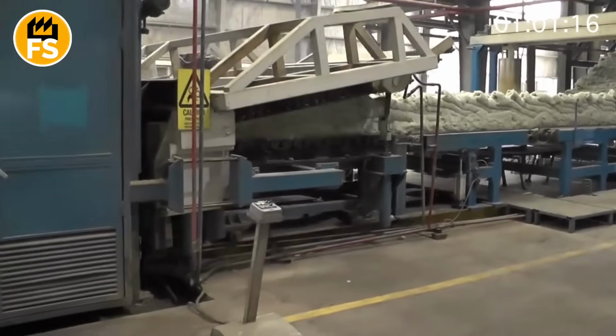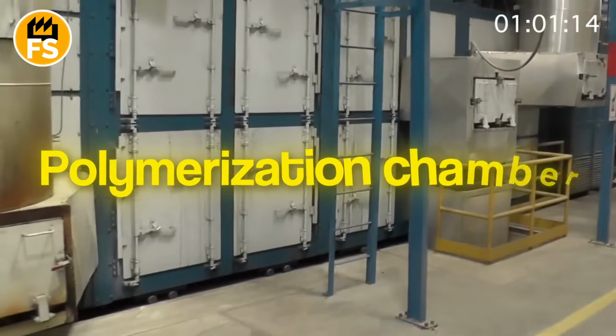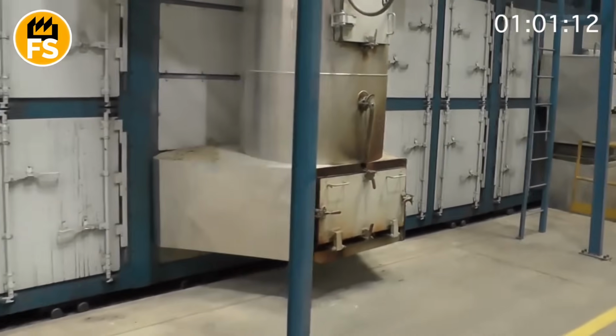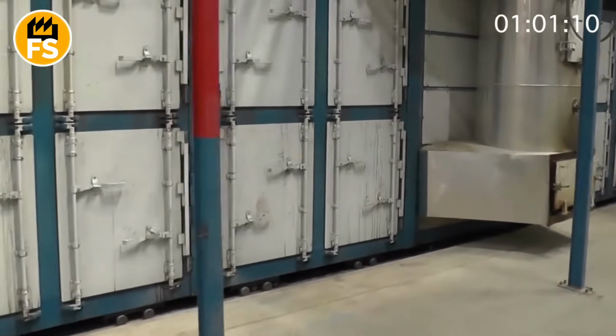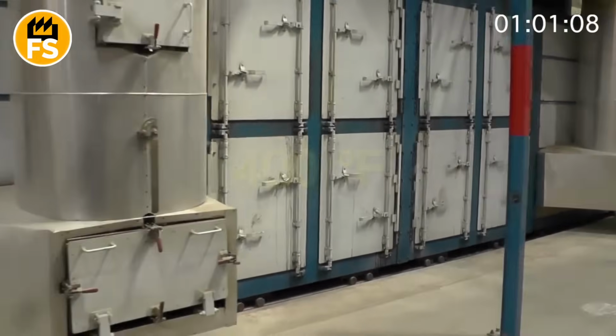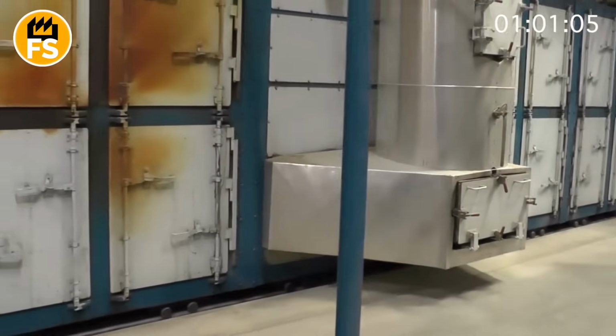It slowly enters a huge furnace called a polymerization chamber. This is a long tunnel, inside which a temperature of about 400 degrees Fahrenheit is maintained. The goal of this stage is not just to dry the mat, but to bake the glue. The resin polymerizes under the influence of temperature. That is, it turns into a hard, durable plastic that firmly glues the stone fibers together at their intersections. It is in this furnace that mineral wool acquires its final properties.